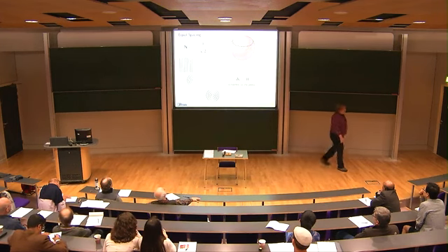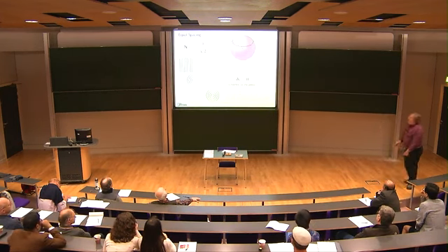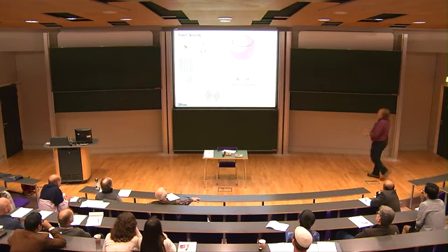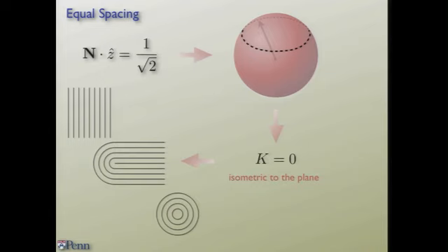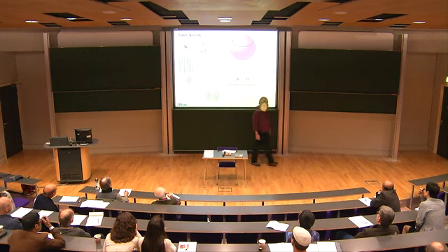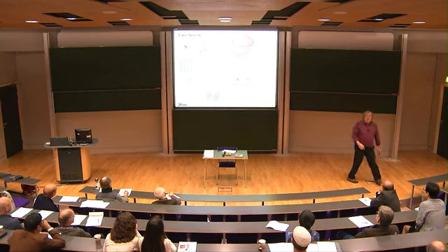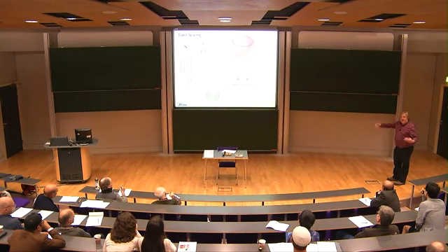So unlike things that were said at meetings that I can't say anything about, I have just proven to you that these are the only 3 textures that can be equally spaced. It would be impossible to take a -1 disclination in 2 dimensions and construct an equally spaced thing without introducing cusp lines. So when I say without, I mean these are the things I can draw as long as the layers are nice and smooth, with no cusps. So that's kind of a nice result. -1 defects cannot be equally spaced unless you also have focal lines.